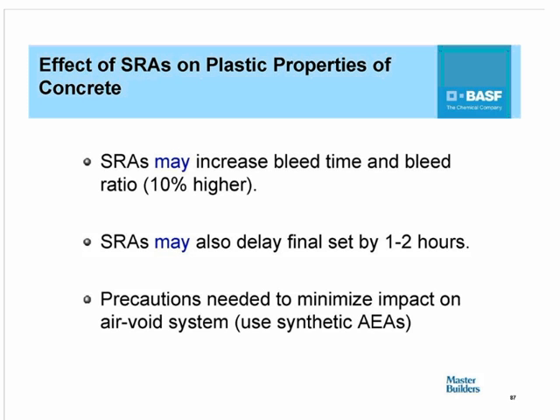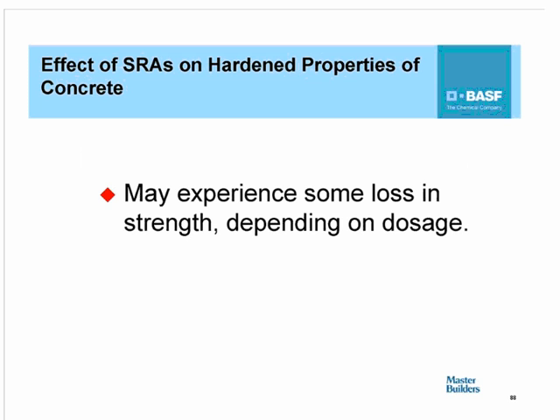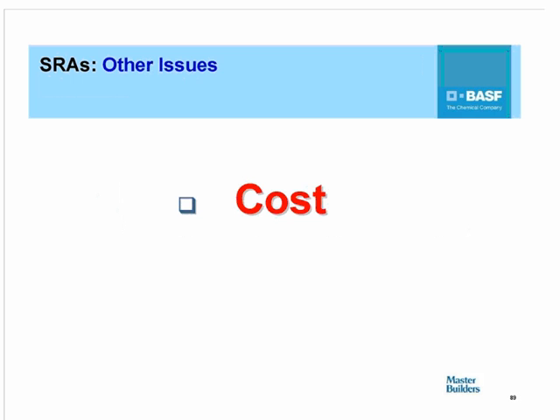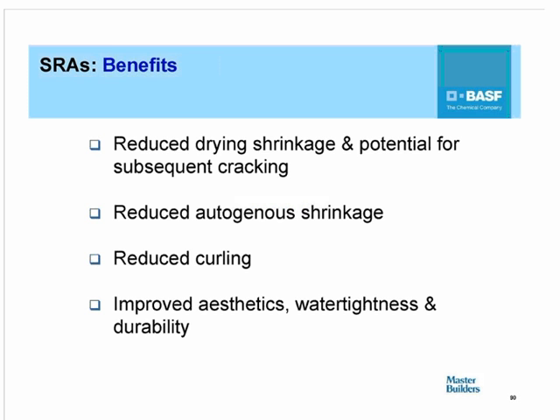They can also have an impact on the air void structure, and as a result of that, most manufacturers or suppliers recommend the use of synthetic-based air entraining admixtures when shrinkage-reducing admixtures are used. In hardened concrete, some loss in strength may be experienced depending on the dosage, but typically it's very minimal. Other issues, the cost of these materials. Just like the lithium-based admixtures, these are fairly expensive relative to other admixtures that may be used in concrete. But the main benefits, again, include reducing drying shrinkage and the potential for subsequent cracking, reducing curling, and then also providing water tightness and improving durability overall.